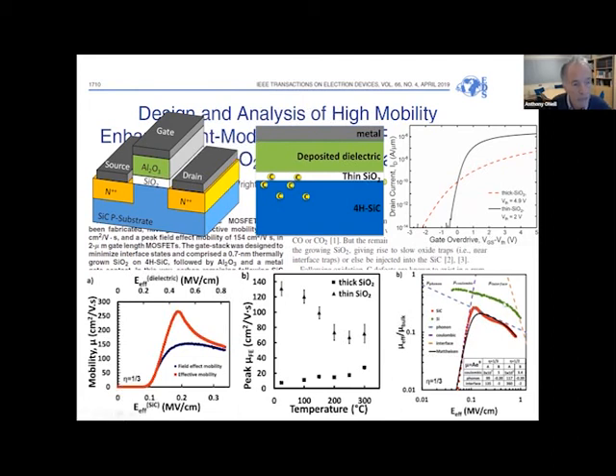This is the silicon data, and it doesn't really matter what silicon transistor you've got, you tend to get this universal response to gate voltage. What we found is, in the case of our silicon carbide devices, we're now getting within about 50% of what you can get in silicon. So that's a big, big improvement on the data that you would normally get with the thick oxides, which would be down at the bottom of this graph somewhere. So we were really quite pleased with the fact that we're starting to get something now which is looking like a proper MOSFET technology. And we've been continuing to make progress on that, and we're hoping to get some stuff out in print before too long.